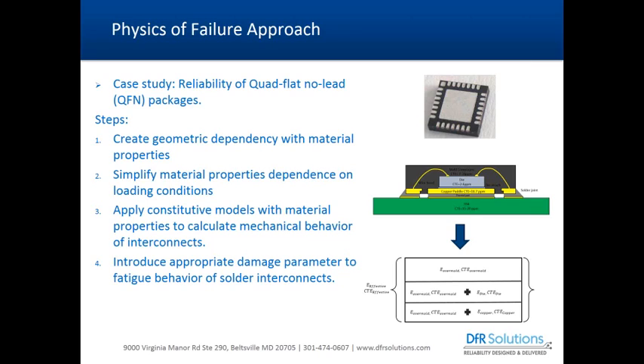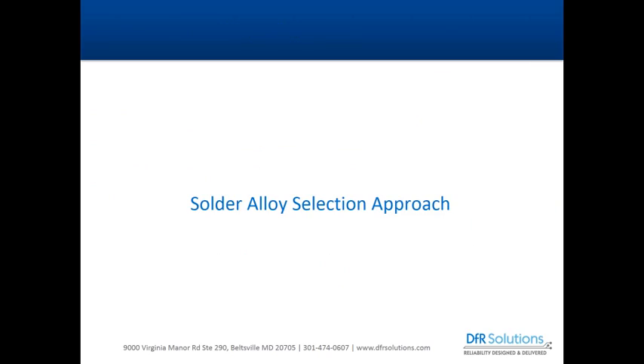For a QFN, we partition the geometry into effective areas and use composite structure theory to calculate an effective property — effective coefficient of thermal expansion and modulus — that are temperature-dependent for your package dimensions and environmental use condition. All intrinsic and extrinsic factors affecting solder joint reliability are accounted for this way.